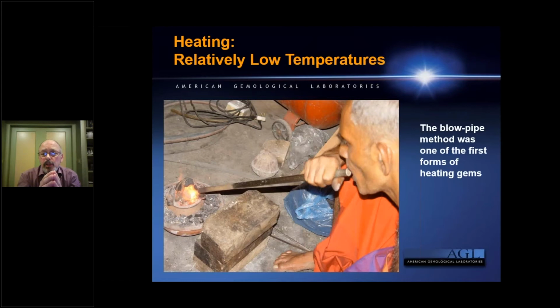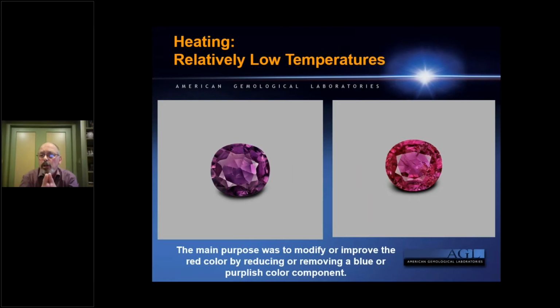So when we talk about relatively low temperature heating, we're talking about heating with a fire. We're talking about blowpipe. This is something that's been used for a very long time to alter or to treat corundum. And when we talk about relatively low temperature heating, we're really talking about color manipulation. And so relatively low temperature heating, especially when we're talking about rubies, is very efficient and very effective at breaking the charge transfer between iron and titanium, which produces the blue color in corundum. So you can have a purple sapphire change into a ruby. You can have a purple sapphire change into a pink sapphire. You can reduce or eliminate a purplish component which is present in stones, and this can all very, very effectively be accomplished at relatively lower temperatures.